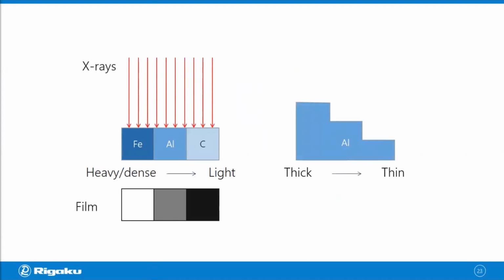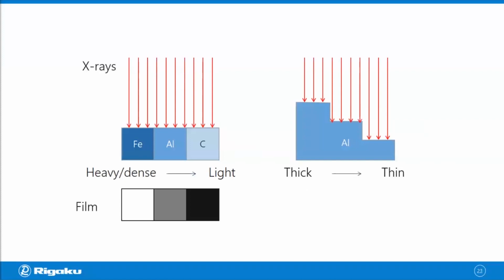If you look at a sample like this, it's all aluminum, but the thickness changes. And you put X-rays through it, put a film underneath, you're going to see something like this. And this is because the thicker the object is, the more X-rays are absorbed. So you can see that the absorption rate is density dependent and also thickness dependent. And that's how 2D absorption imaging works.